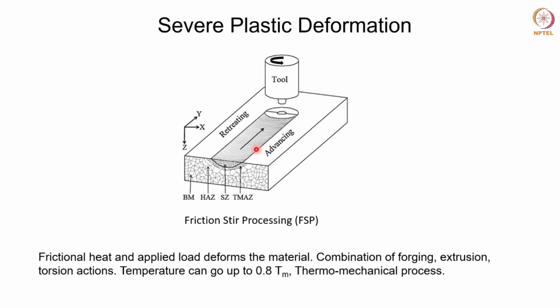So if you have welding to be done, then as I said, you will have two plates and this tool will be moved along the joint line leading to a joint between the plates. But in case of friction stir processing, only a single plate is used. So all the mechanical energy of this tool goes into deforming the material, leading to grain refinement. And the temperature in this case can go up to 80% of the melting point, and hence you can say that this is a thermomechanical process, right? A thermomechanical process, as you might know, is a deformation process which is done at high temperature.